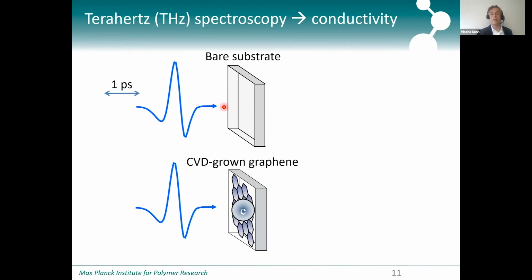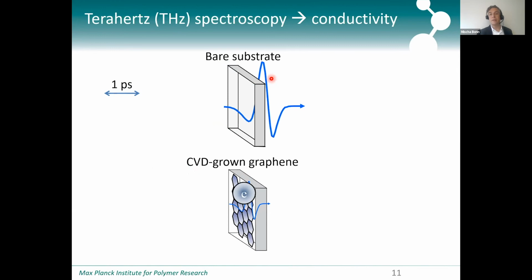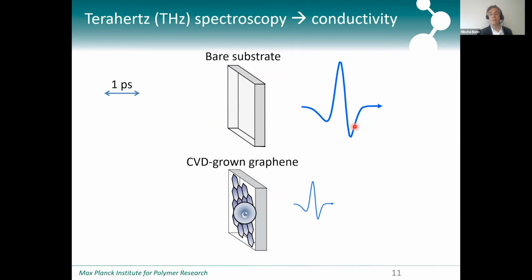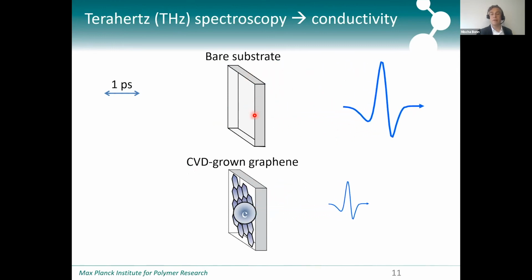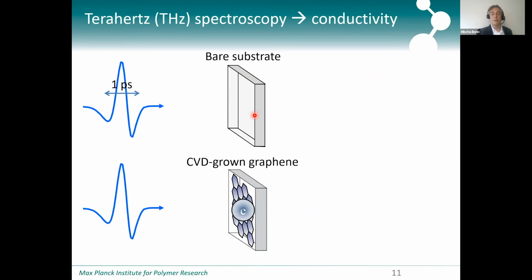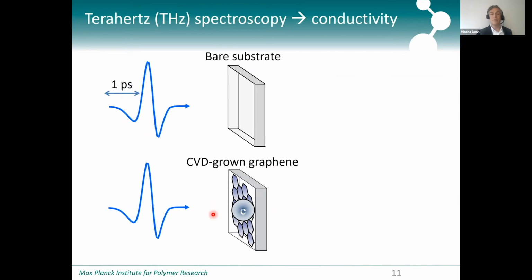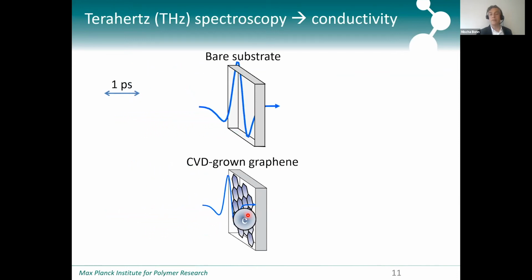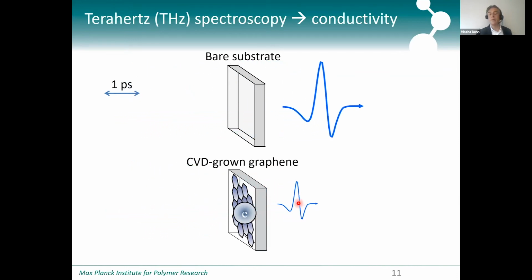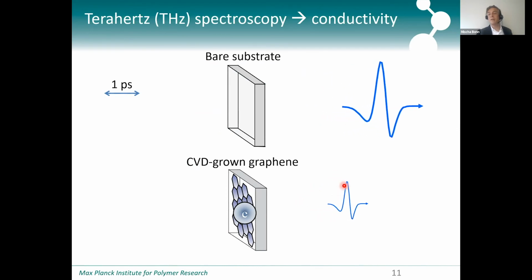So here's the terahertz pulse hitting the bare substrate, and there's no interaction with the substrate. But if I run the movie again, you can see in this case there are carriers. Those carriers are accelerated by the field, and in that process the field loses some of its intensity. So some of the power, or the intensity, that is in this pulse is now transferred to the system and is dissipated as heat.